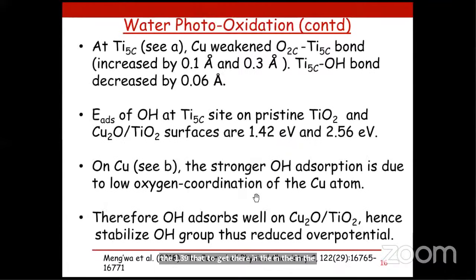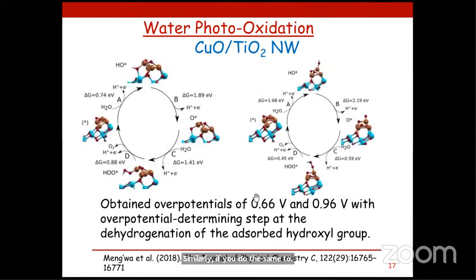Similarly, if you do the same for CuO over TiO2, the potentials are again reduced, and you'll obtain potentials of 0.66 volts and 0.96 volts. And we realize that the potential determining steps are at the dehydrogenation of the adsorbed hydroxyl group.